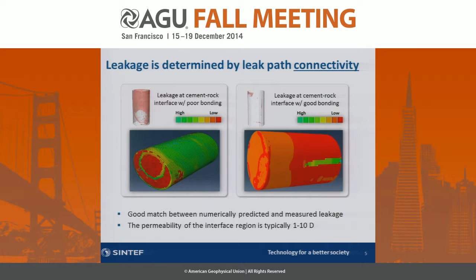And then when we have all these leakage paths that are mapped by micro-CT, then we can use these directly in for simulations. So we can actually import the micro-CT volume into Abaqus to do flow simulations. So this is where you had a lot of leakage paths. You can see that with the green here, that's a high flow velocity. And this is single phase flow, just steady state flow that we simulated here.